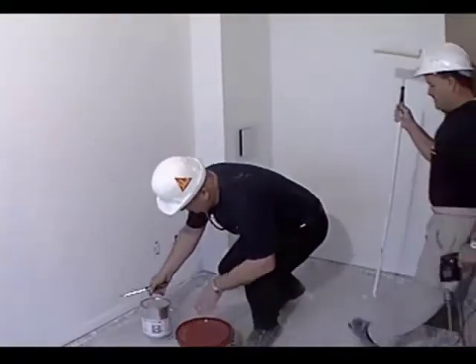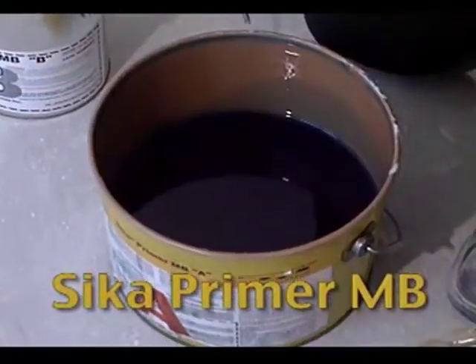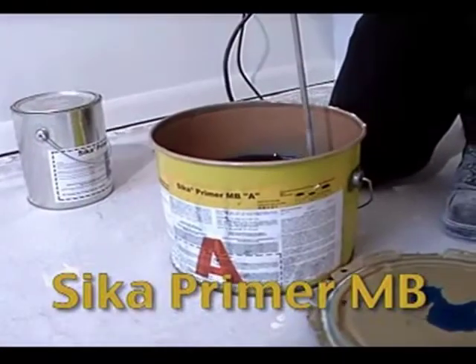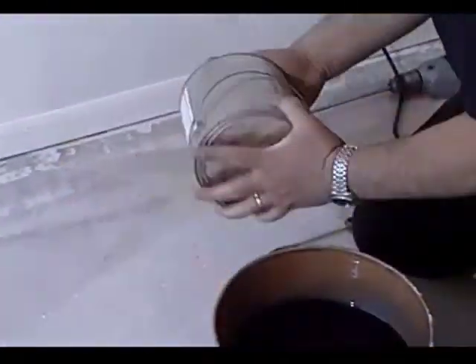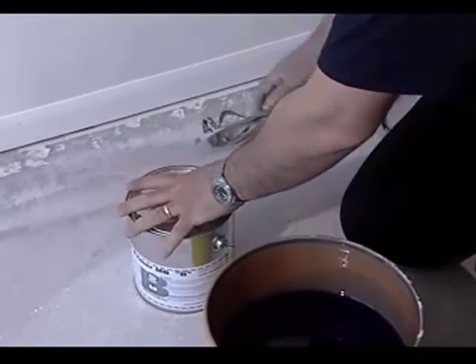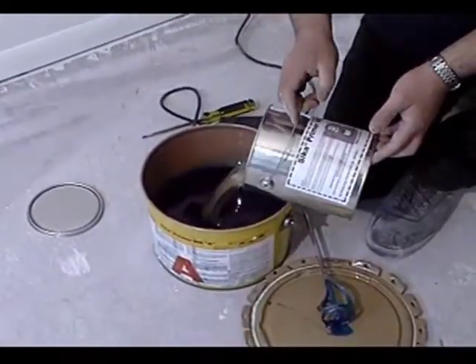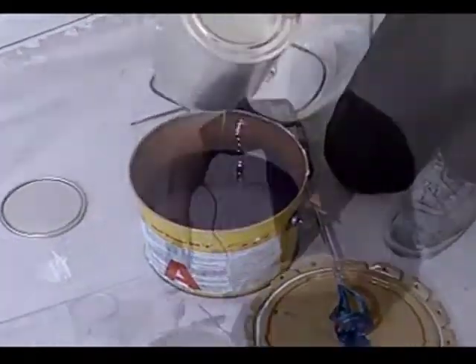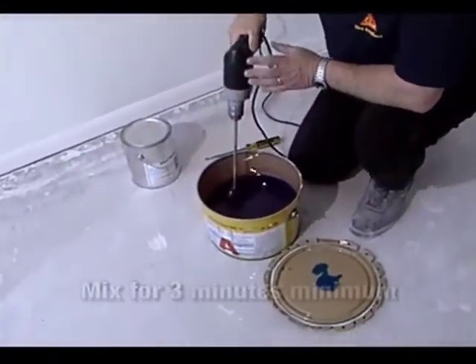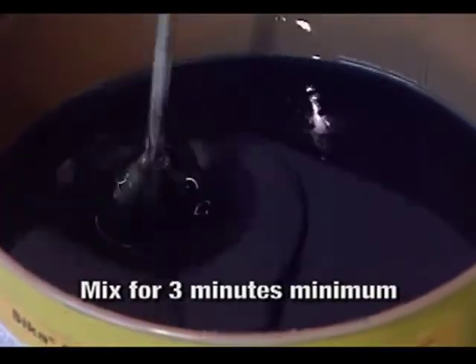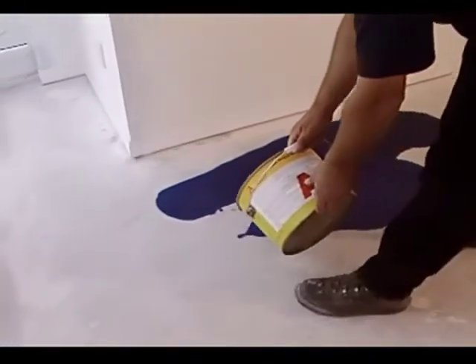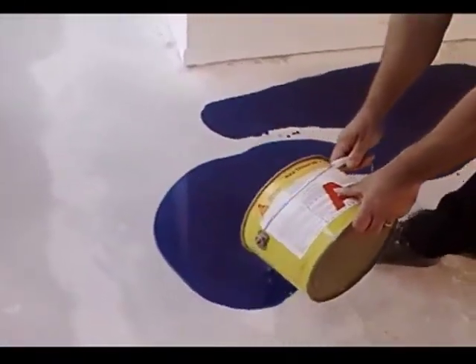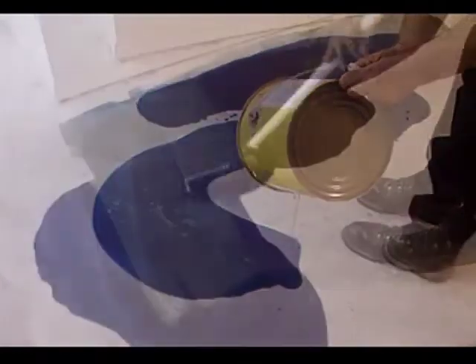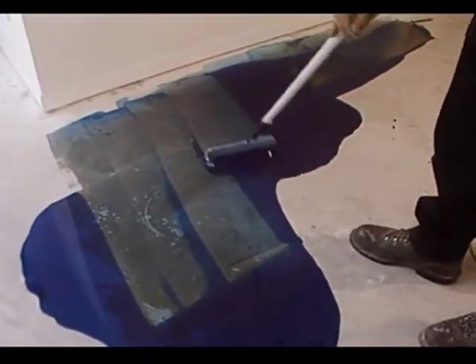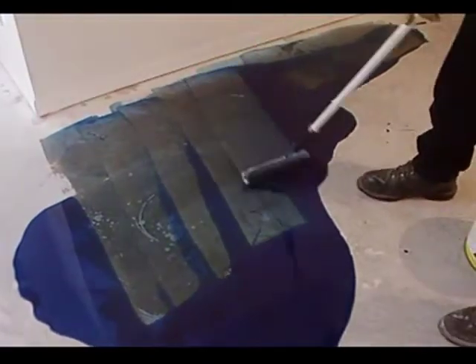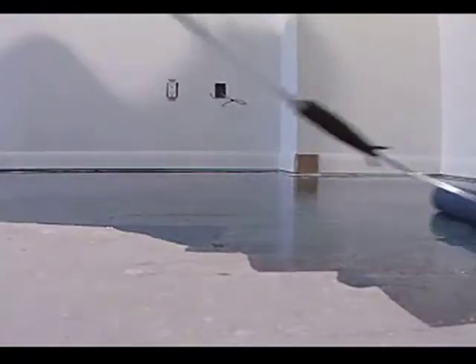The solution to moisture problems is Sika Primer MB. This product is a moisture retarder designed for on-grade concrete slabs and is an important part of Sika's systems approach. Sika Primer MB is a low-viscosity, solvent-free moisture regulator, effective in conditions of up to 6% moisture using Tramex. MB also works well as a substrate consolidator for gypsum-based concrete and is effective on old porous concrete slabs. Sika Primer MB is also an excellent adhesion promoter for previously coated slabs.